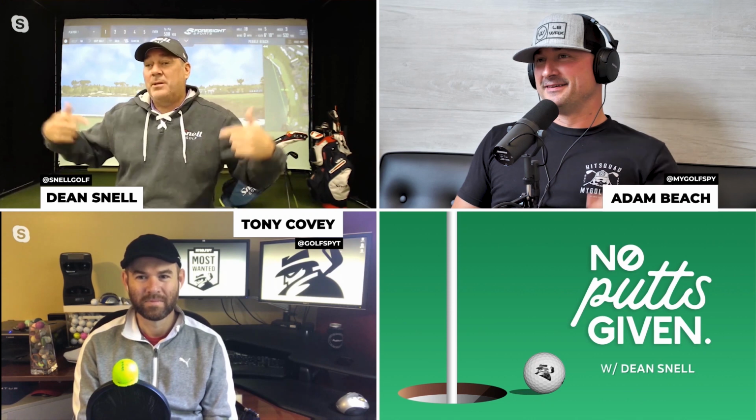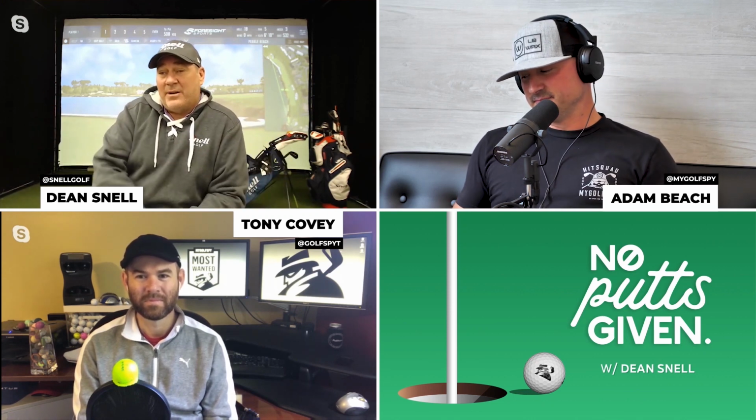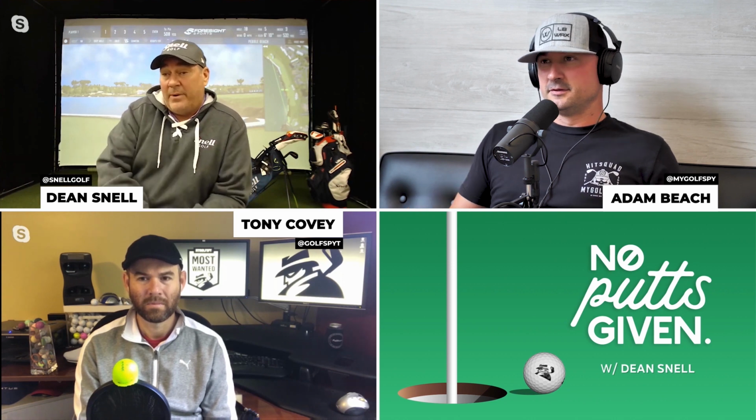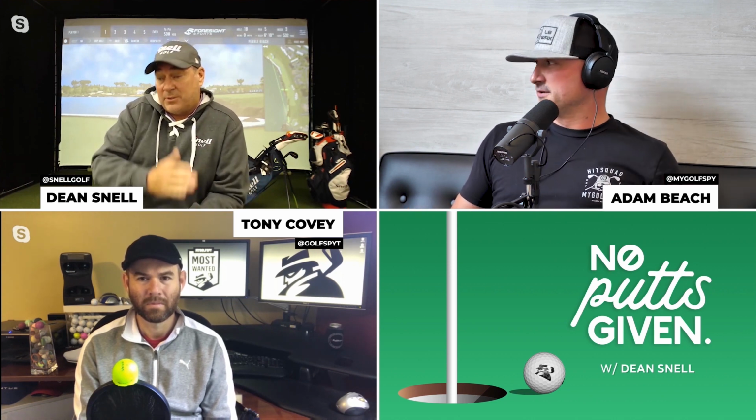We had to teach the people on the manufacturing side how to do urethane. It's an extremely difficult process. Remember, cast urethane is A and B together, an exotherm reaction that cross-links, so it's irreversible. You can't remelt it. You can't reuse it like the thermoplastic urethane. It cross-links and creates a very tough cover, so you can go a little thinner, and the durability got a lot better. You might want to tell that to Costco on that Kirkland ball.